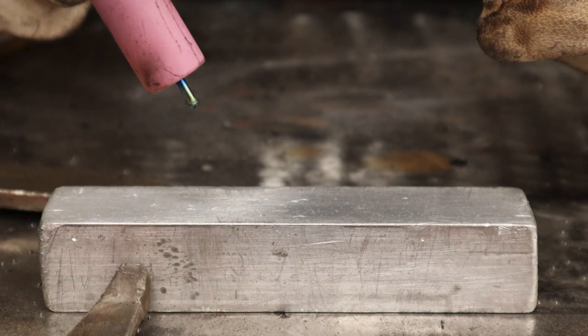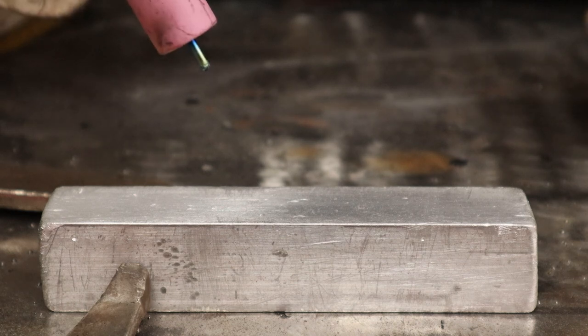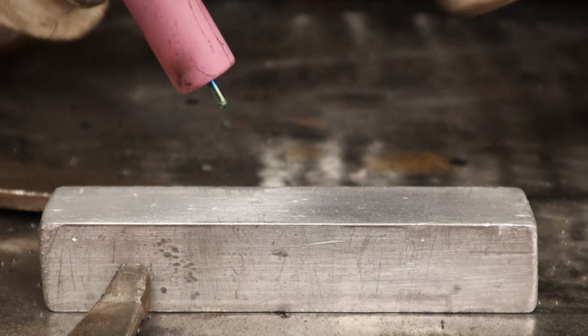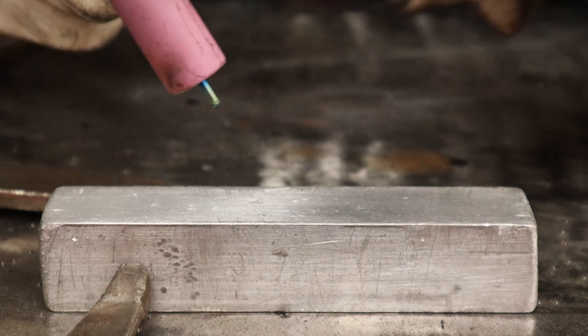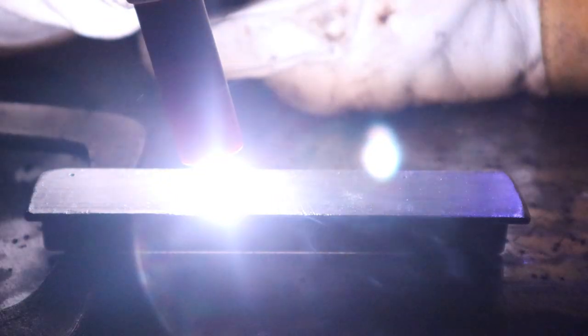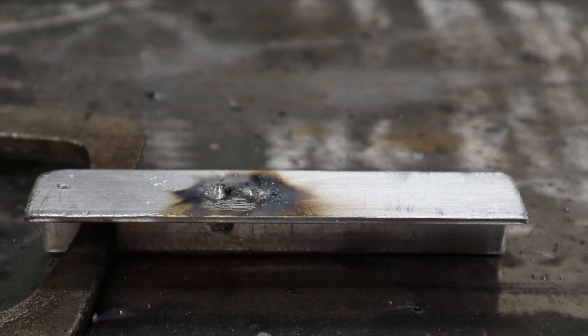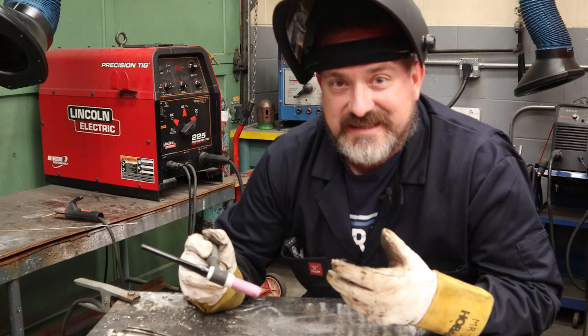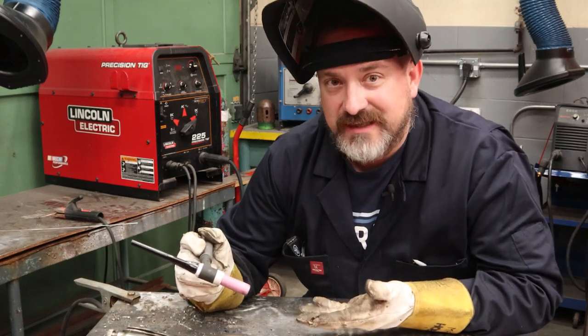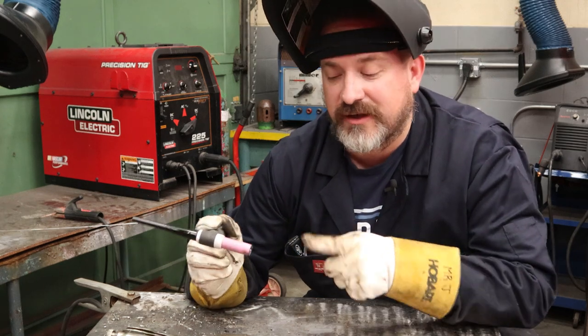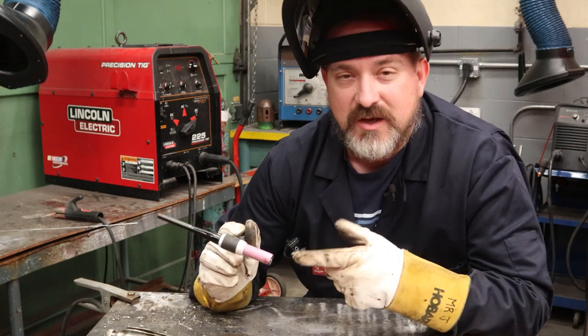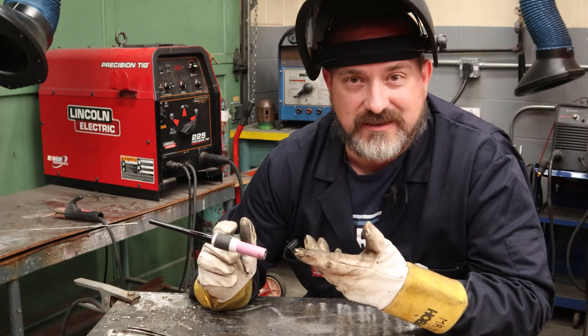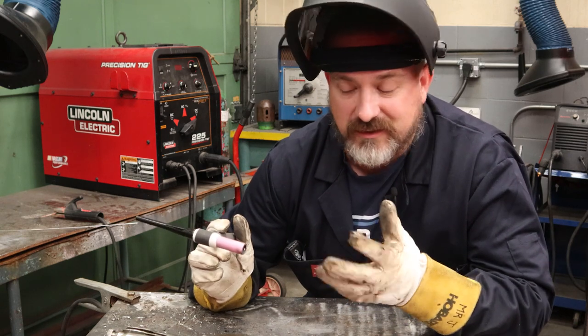So this is DC positive, so we're gonna see what happens and we can talk about it after. However, I am gonna give you a little hint. Keep an eye on that electrode because it's gonna happen pretty quick. Poof! There it goes. Ew, we literally have tungsten put right into that aluminum weld. Yuck. Now with DC positive, you have all of the electricity coming up from the aluminum material and going into the tungsten electrode, which explains why within seconds this got too hot, melted, and exploded on us.